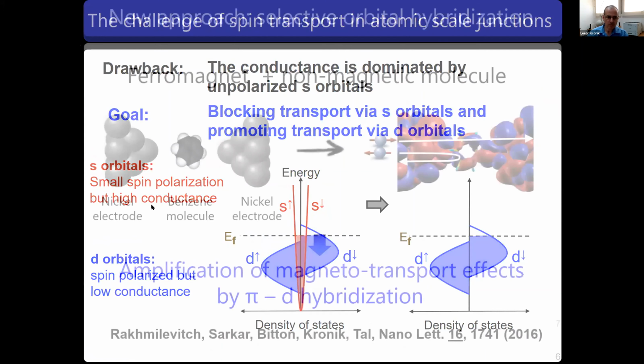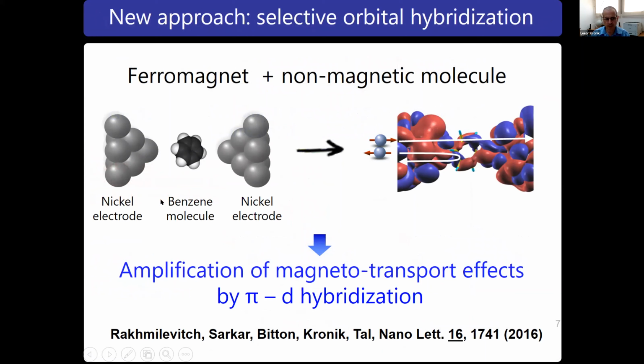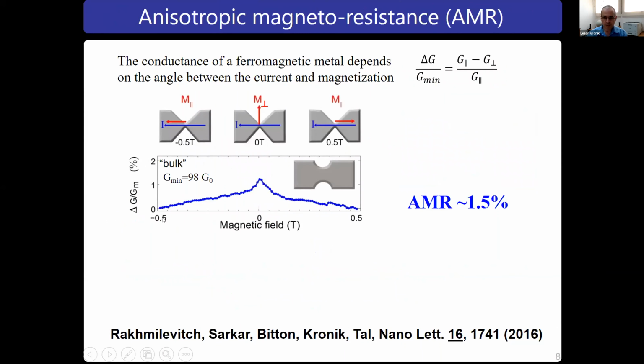Now it's the same molecule in the middle, benzene, as before, except that now the metallic lead is nickel, which is obviously magnetic. And the question is whether there is an amplification of magnetotransport effects via this pi-d hybridization. Oren's group measured that through anisotropic magnetoresistance, namely the idea that the conductance of a ferromagnetic metal would depend on the angle between the current and the magnetization. This is a known effect, albeit a small one, even for bulk nickel. It's just 1.5% or so, but it's an indicator of spin polarization.